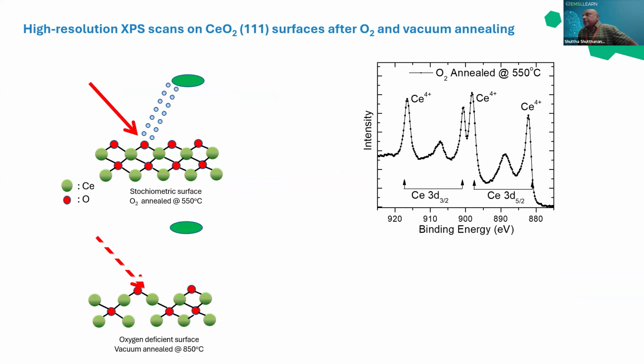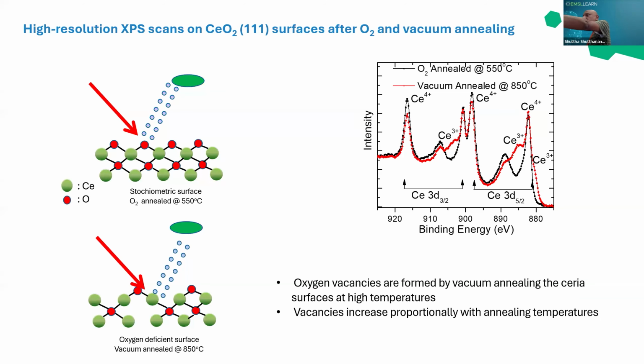So here is the typical XPS spectrum from the first one. The black one is from the fully stoichiometric surface. You can clearly see that is the spectrum I showed you earlier. And then when you have a reduced surface, you see a mixture of cerium 4 plus and cerium 3 plus. Okay, go ahead.